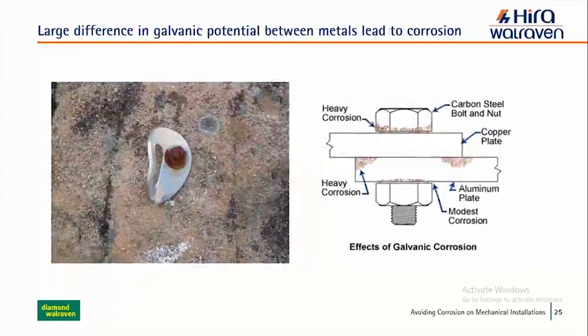To revisit galvanic corrosion: when you have two dissimilar metals with an electrical conducting connection and a common electrolyte, you'll have galvanic corrosion. Either anodic metal dissolution or cathodic oxygen reduction will take place almost exclusively in one metal. As shown in the picture — a fastener connecting copper and an aluminum plate — copper is a much nobler metal, so it will not corrode, but it will accelerate the corrosion of carbon steel and the aluminum plate. You'll see heavy corrosion in the joints between the copper plate and aluminum. The fastener will fail near the copper plate zone.